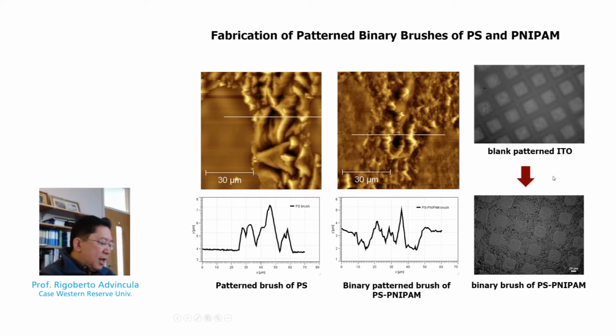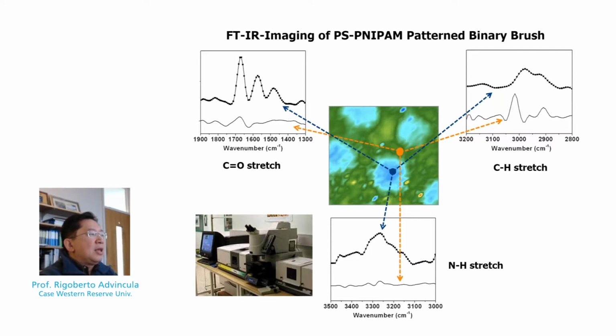Now, what's interesting is that this modification, of course, does not reveal the chemistry. But what's more interesting is if you apply a technique called IR imaging, the image or morphology change on the brush can be distinguished by the IR spectra that we observe by IR AFM, with the green color revealing that of the polystyrene grafted polymer, and the blue color revealing that of the poly-NIPAM (PNIPAM). Hence, with a combination of AFM and IR microscopy, one can have a distinct characterization of both the morphology and the chemistry associated with the grafted polymer brush.